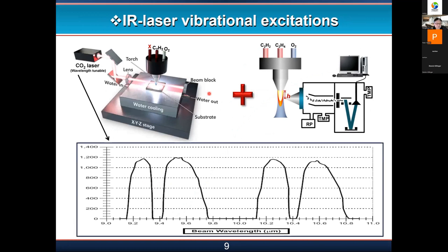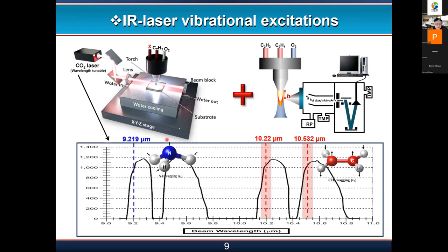So what we did was to look at what the laser excitation of different vibration modes means to the chemical reactions. We use optical emission spectroscopy or open air mass spec to look at chemical reactions, what products are being produced, and what intermediate states are being promoted by the laser excitation. For example, these are the 4 wavelength bands from CO2 lasers, from CO2 molecules. We can generate the 4 bands in this Bragg curve, and then we can resonate, for example, the wagging mode of C2H4 molecules at 10.532 micrometer at this point, or to ammonia molecule.